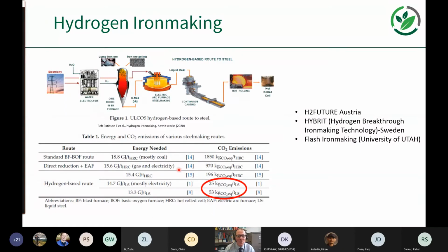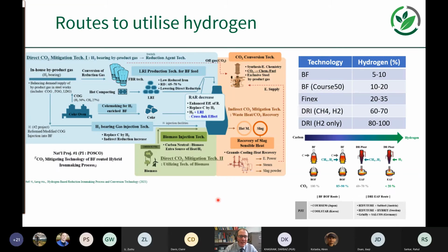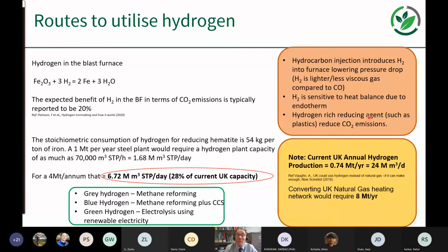So I mentioned hydrogen briefly. Of course, hydrogen really has stellar potential to reduce CO2 emissions, and there are a couple of hydrogen projects in the pipeline at the moment in Austria and in Sweden, and there's significant potential to reduce the emissions of iron production using this hydrogen-based route. There are a variety of different ways it can be incorporated into the blast furnace, but there's a limit to what you can put through the blast furnace. It can be incorporated at a much higher level in direct reduced iron production, or potentially, if it's used as the only gas in direct reduced iron production, it could be very high incorporation, and then the associated CO2 emissions would be much lower.